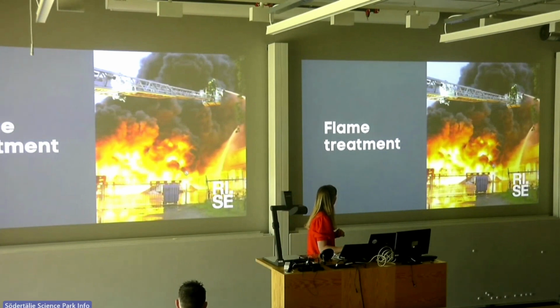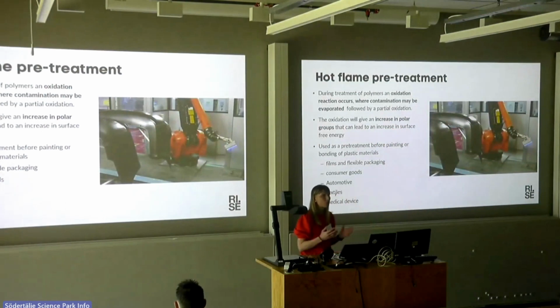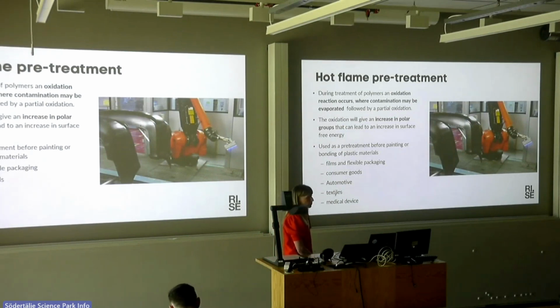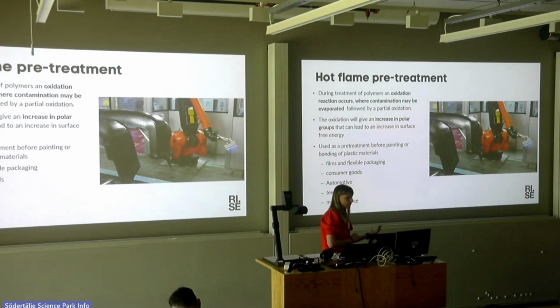So let's go on to the next one, flame treatment. It should not look like this, but sometimes you have the feeling that it's what can happen when you have a flame that is several centimeters in open air. Hot flame pretreatment here is mounted on a robot, ready to treat plastic components. With the hot flame, you get oxidation, and you can evaporate contamination on the surface, of course. You also increase the polar groups on the surface, and as with plasma, you get better wettability and bonding to the coating or next step.